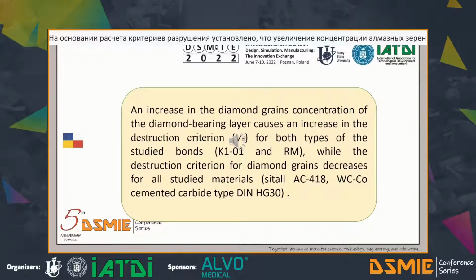The results of the calculation showed that an increase in the diamond grain concentration of the diamond-bearing layer causes an increase in the destruction criterion for both types of the studied bonds, while the destruction criterion for the diamond grains decreases for all studied materials, sital and cemented carbide.